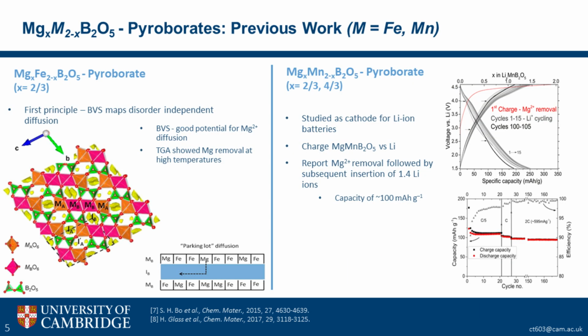So I'm going to present some seminal papers that were done on these classes of materials. If I'm not mistaken, this paper was written by Shuhang Bo at the beginning of his career. And so this studies a magnesium-iron pyroborate with a stoichiometry of 2/3 magnesium, 4/3 iron. This was a first principles study where, by looking at bond valence sum maps of the material, they were able to identify these channels for magnesium diffusion that you see here.